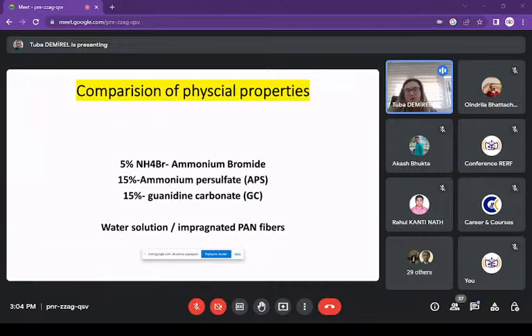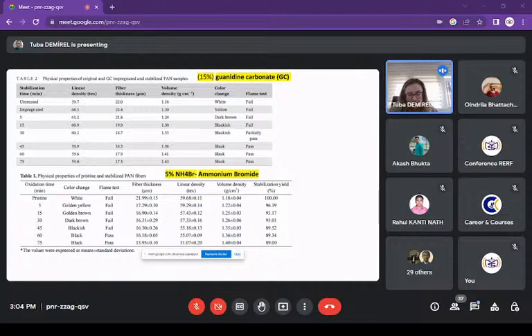5% ammonium bromide in water solution, 15% ammonium persulfate in water solution, and 15% guanidine carbonate in water solution. Then the raw material, the precursor PAN fibers, is impregnated. Then we compare the physical properties of guanidine carbonate and ammonium bromide.